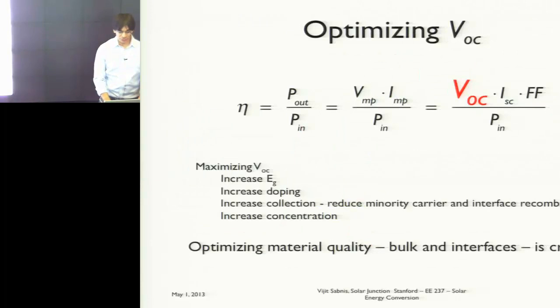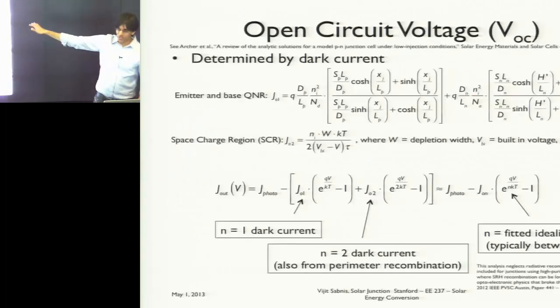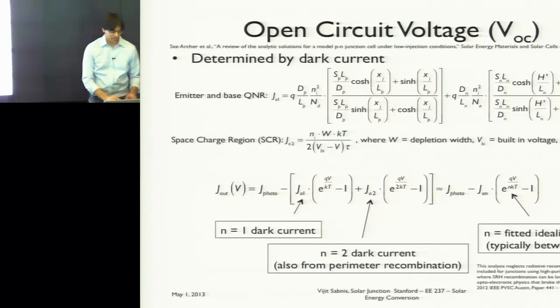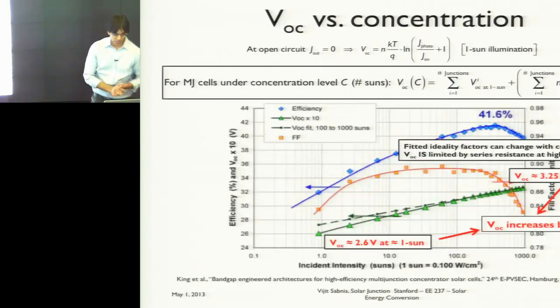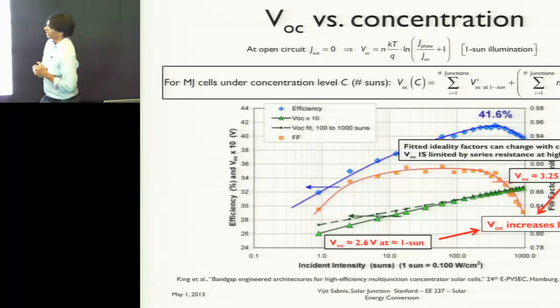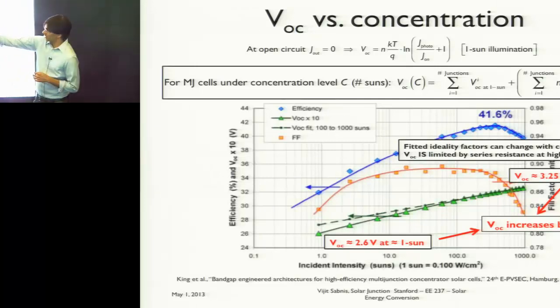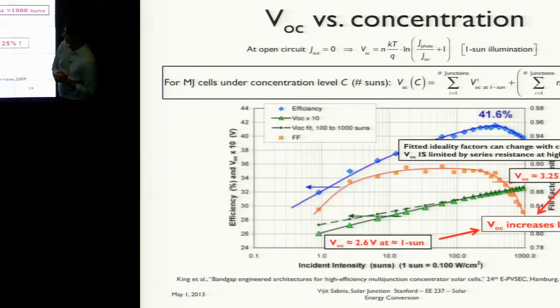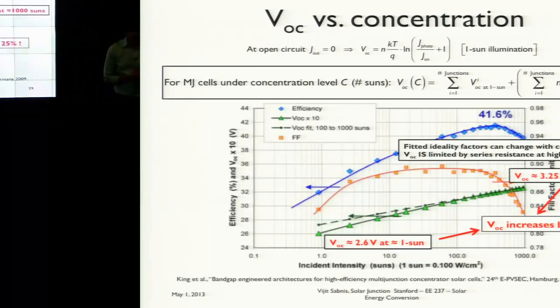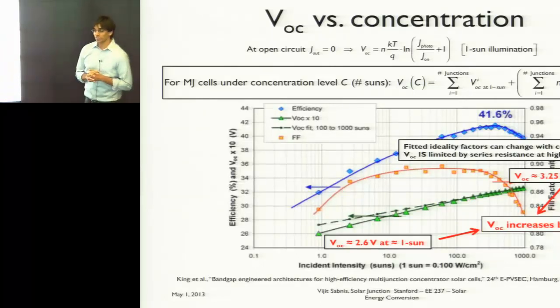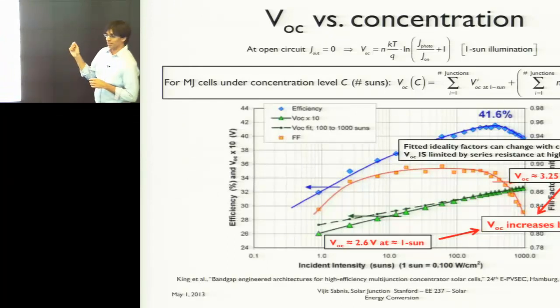Let me then move to the open circuit voltage. You've got the traditional dark current equations. There's nothing different here other than you have to optimize your dark current for each of your individual junctions. Now, this is the key point. I mentioned this earlier. If you look at efficiency, VOC, and fill factor versus concentration, one of the remarkable things that you'll find is that your VOC at 1 sun in this particular solar cell is 2.6 volts, and at 1,000 suns, it's 3.25 volts. That's a 25% increase in voltage.